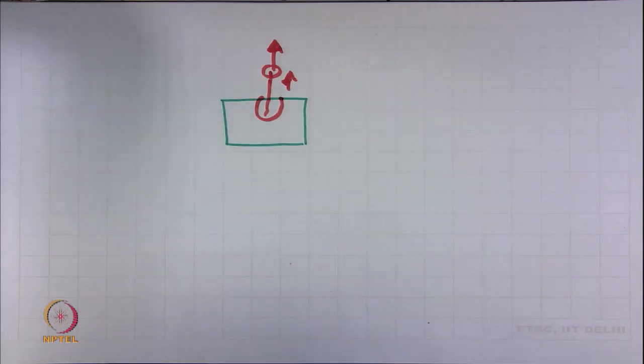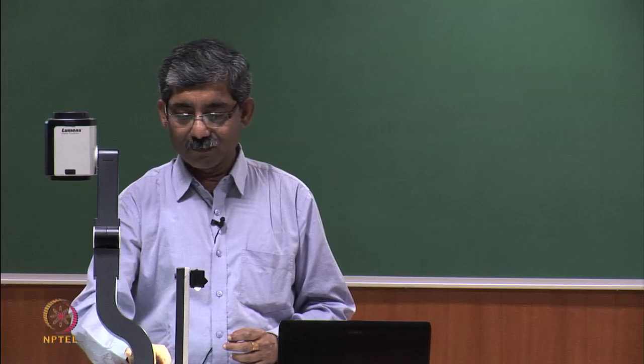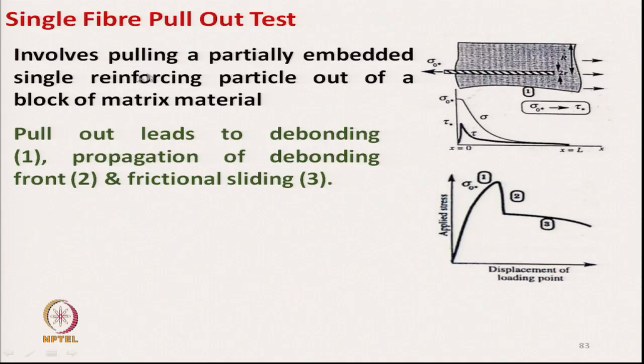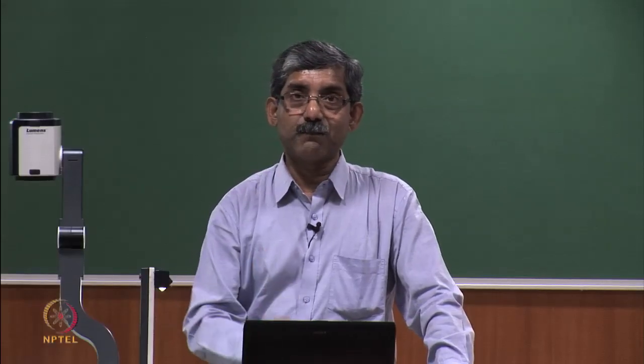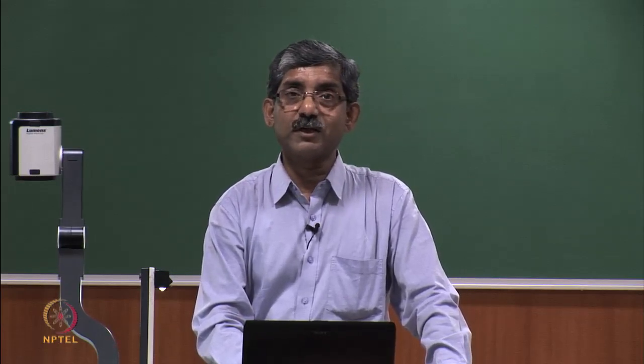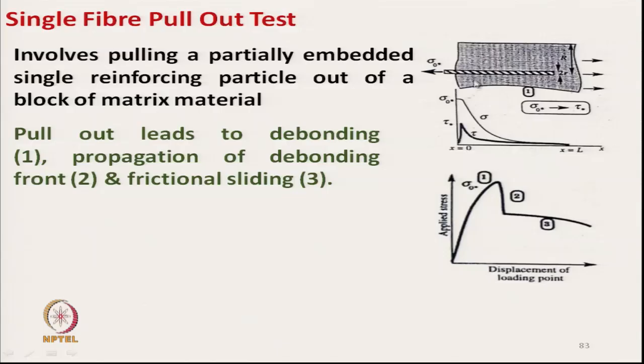That means, if the fiber breaks before it comes out, then the test method will not be complete. So, a partially embedded single reinforcing particle, like here the particle is the fiber, is pulled out of the block of matrix material, this portion. Pull out leads to debonding. First debonding takes place, then the propagation of the debonding front, and once the debonding and propagation are completed, then frictional sliding will be there. This test is applicable when the strength of the reinforcing material is very high, higher than the bonding strength.